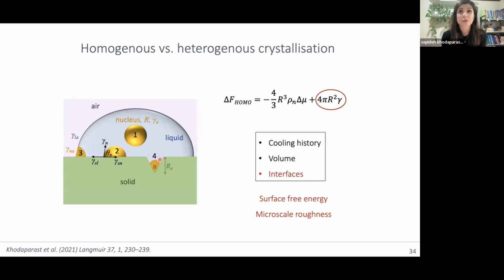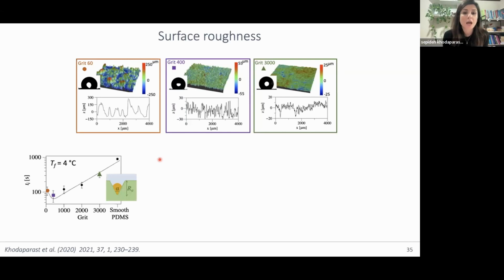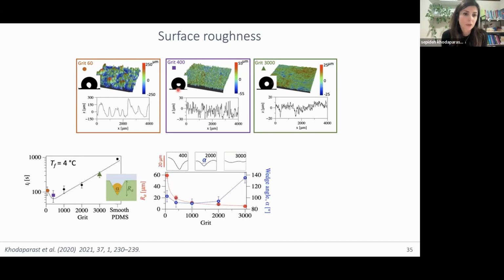What if we add surface roughness to the scenario? The majority of the surfaces that you deal with, unless it's very smooth glass, such as metallic surfaces, typically have quite large roughnesses depending on the machining technique that you use. These are surfaces that are created by casting sandpaper, and sandpaper has a grit number: the larger the grit number, the smaller the surface roughness. If I plot again the time it takes for the first crystals to form versus the grit number of the sandpaper or the rough surface,